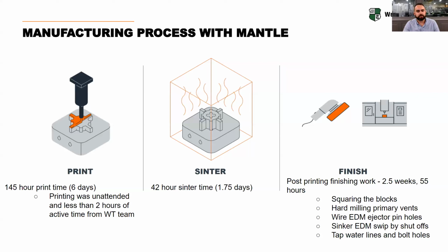From there, we had to do our 42-hour sinter, which got our blocks up to the 42 Rockwell. And then once we got the parts off the printer, you can see some of the areas that we had to work on, which took us about 2.5 weeks. So obviously squaring up your blocks, hard milling your primary vents, wire EDM, the ejector pin holes, and then sinker EDM, the swipe by shutoffs that were there, right? Really anything that we had to touch was more like an undercut, like your water lines, or any tight tolerances.